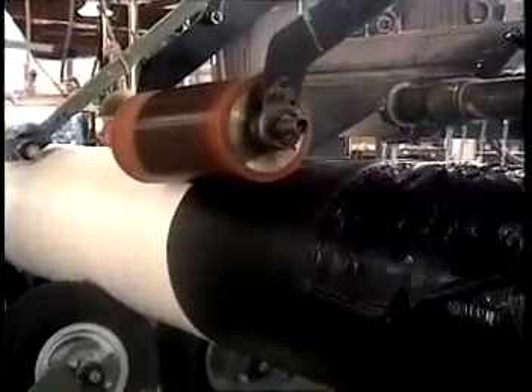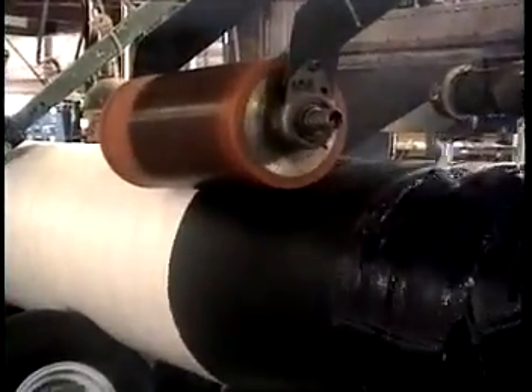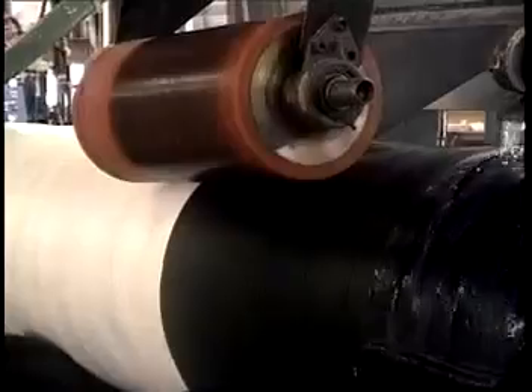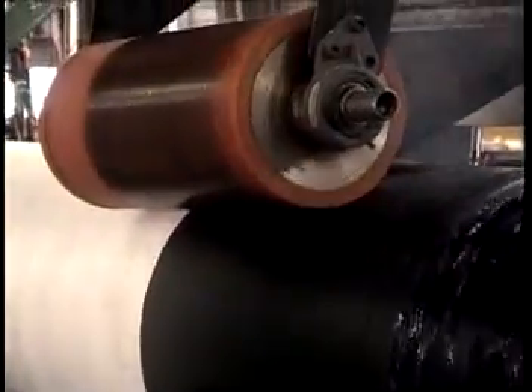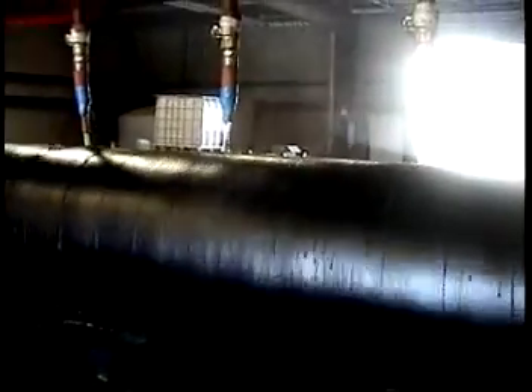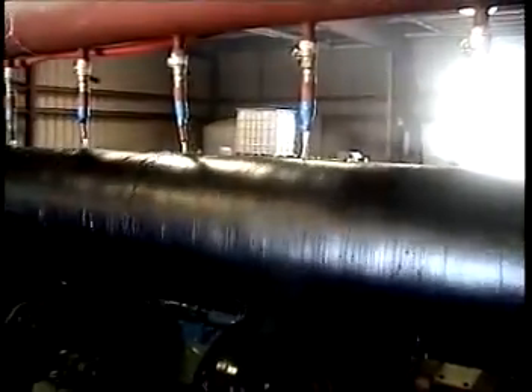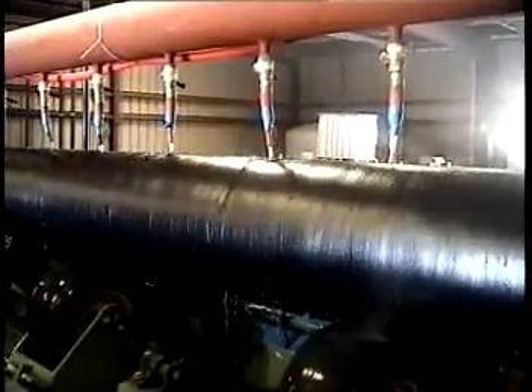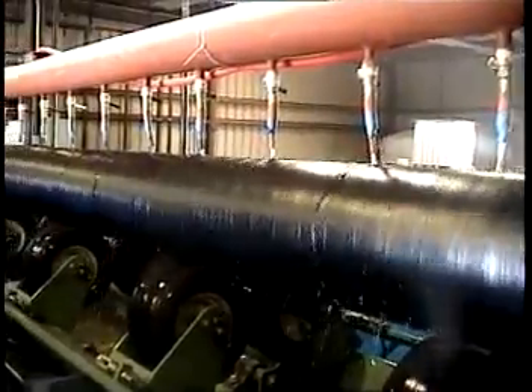Multiple wraps of the molten film result in a seamless polyethylene pipe of the required thickness, in this case 80 mils. A water quench is used to cool the polyethylene. The pipe is fed under a series of water nozzles, and the polyethylene is cooled to 90 degrees Fahrenheit along a distance of 20 to 25 feet.